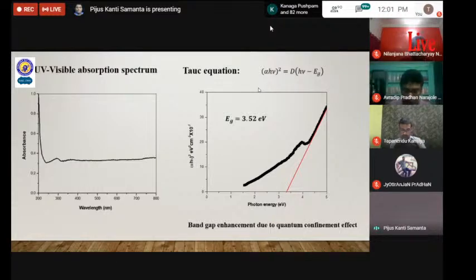The optical properties of the material were studied by observing the UV visible absorption spectrum and photoluminescence spectrum. This graph shows the UV absorption spectrum of the sample, which shows the low absorption property of the material. That means the material is quite transparent, especially in the visible window. And we can use the Tauc equation to calculate the band gap from this UV visible data, where alpha is the absorption coefficient and Eg is the band gap of the material.